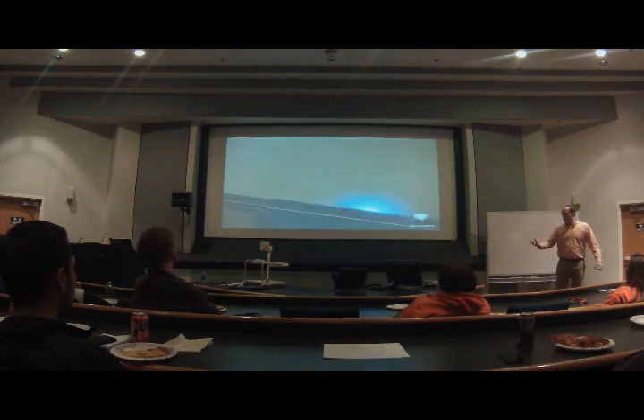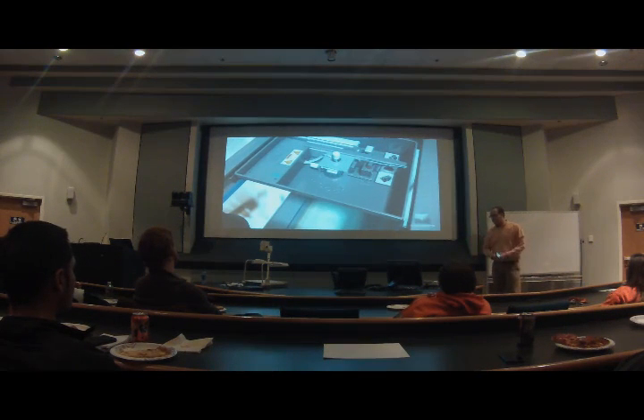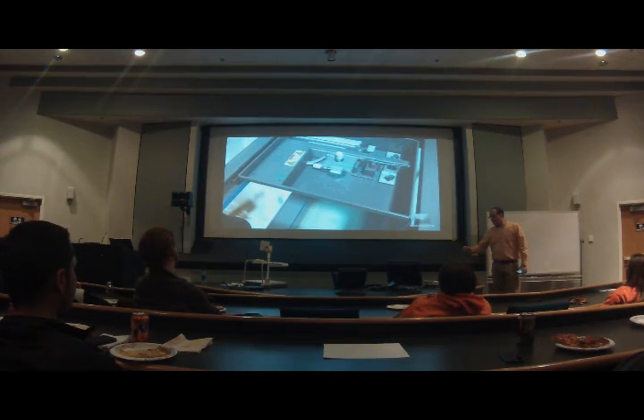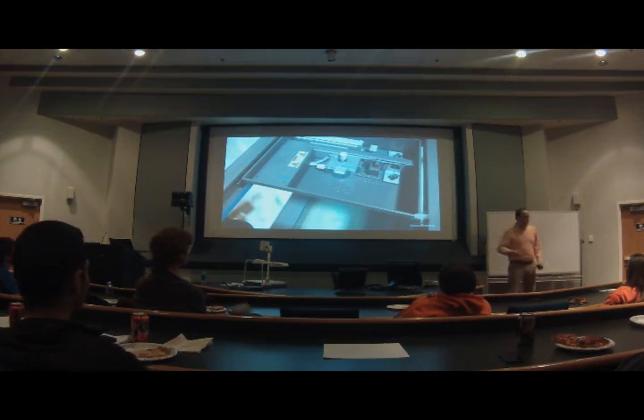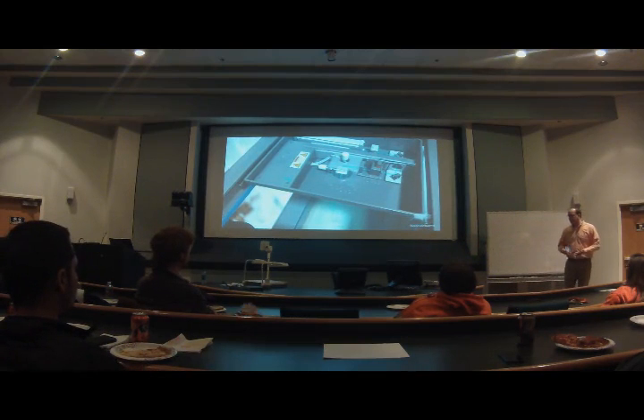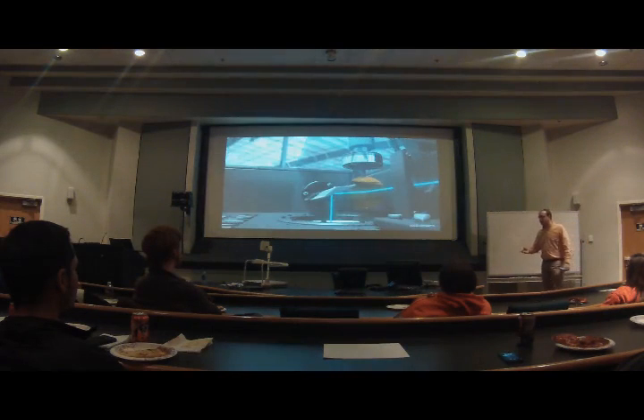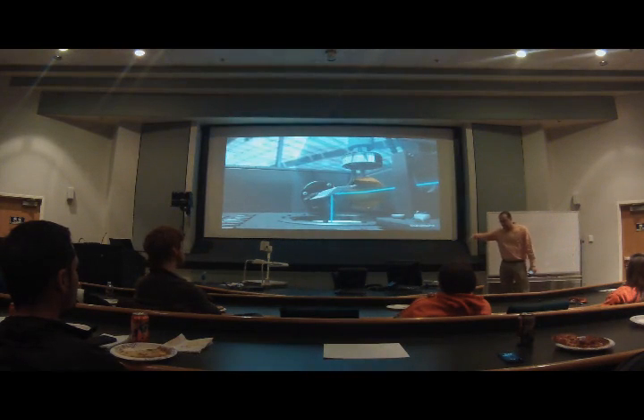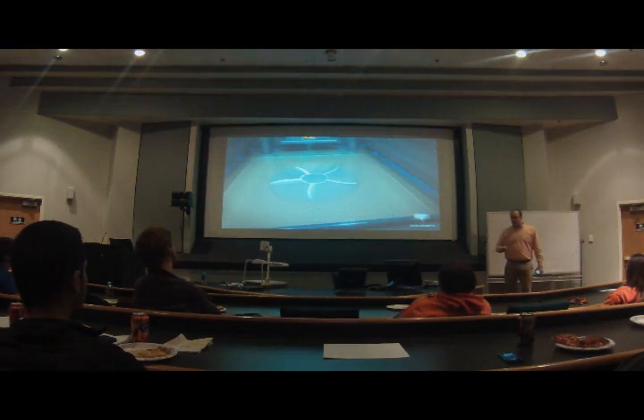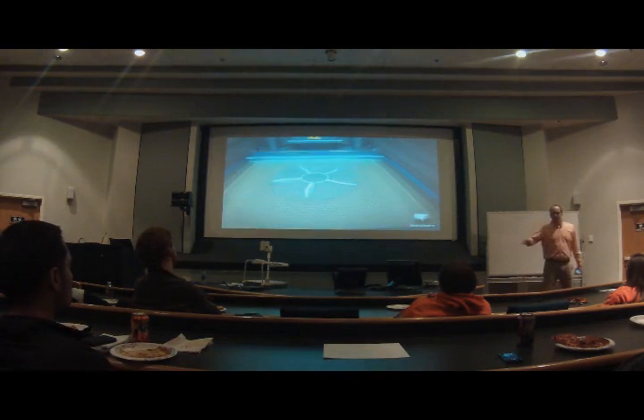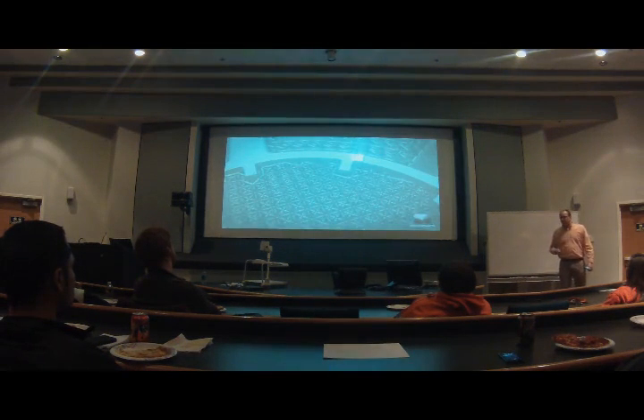But interestingly enough, the build platform descends into this pool of ultraviolet reactive fluid. So the UV laser is actually steered down onto the fluid. You'll see the little motors that steer here, the voice coil actuators that steer the lasers, just actually mirrors that move it around. The laser itself is stationary. And by using mirrors, instead of having to accelerate the big laser head, they actually steer this around incredibly fast. You can lay down a layer fairly quick, and that's good because each layer is extremely thin, like 1/1000 of an inch thick.